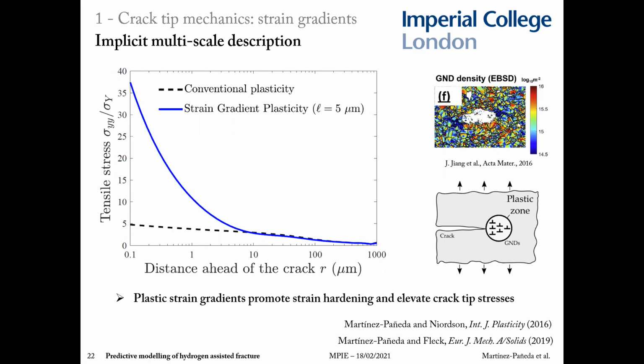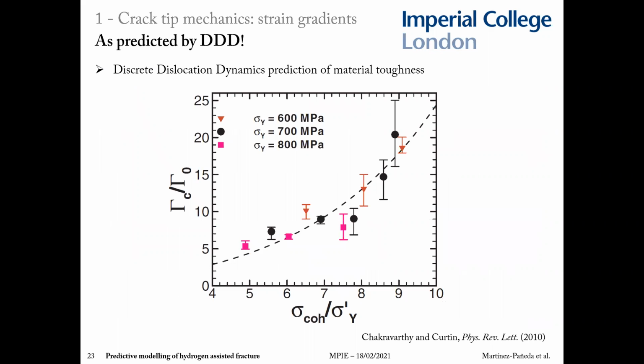And let me remind you that getting these stress levels right is very important, not only because of purely the cohesion or brittle fracture arguments, but also because the higher your hydrostatic stresses are, the more hydrogen will accumulate at that critical distance. And in passing by, let me just say that in a way, this is what you see when you use discrete dislocation dynamics.